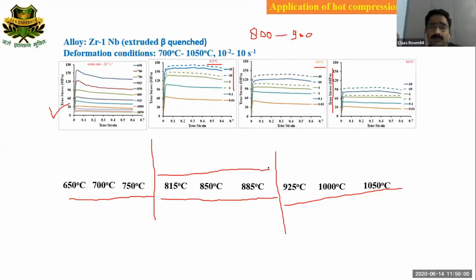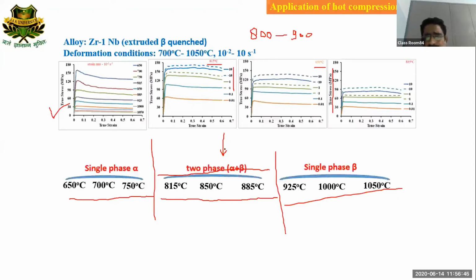Now the question is why I am considering this two-phase domain. Because on the industry shop floor this alloy is normally processed in the two-phase domain, since we have to control the microstructure as well as the mechanical properties. With the help of these processing parameters we can control the proportion of alpha phase as well as beta phase. That's why I am focusing on this temperature range which lies in the two-phase domain. It is well written: alpha phase, two-phase and single beta phase.